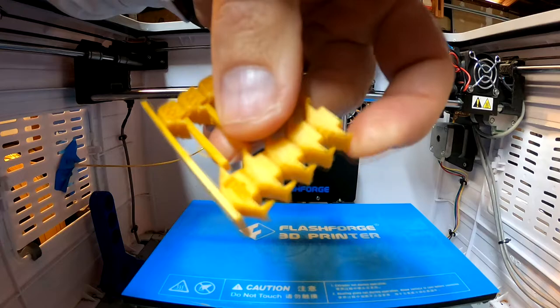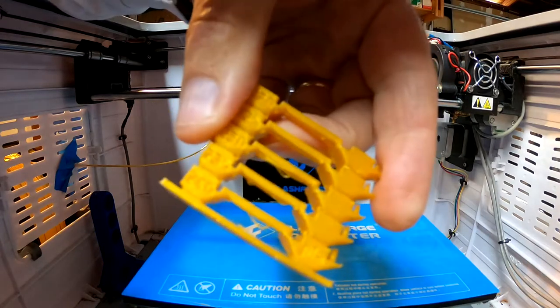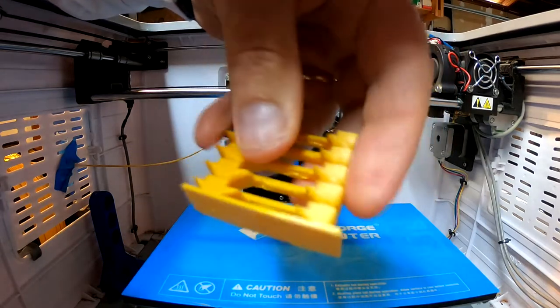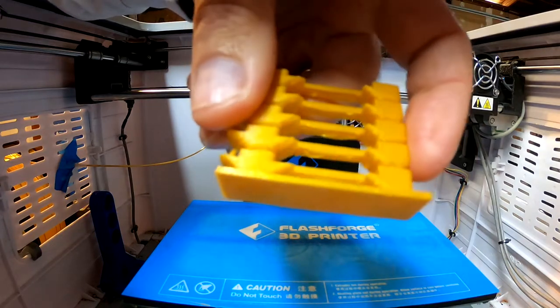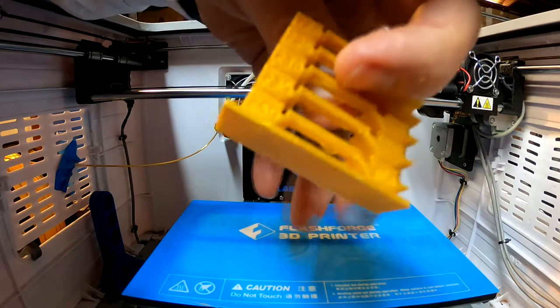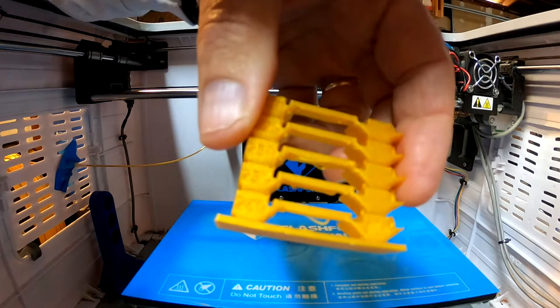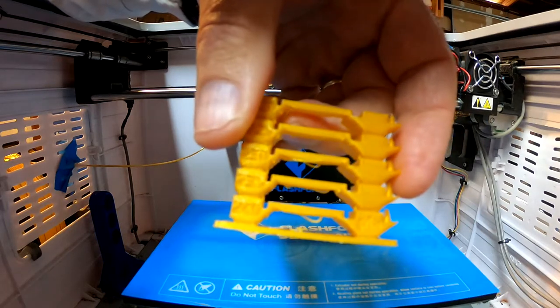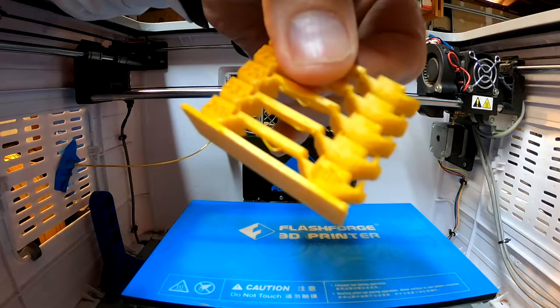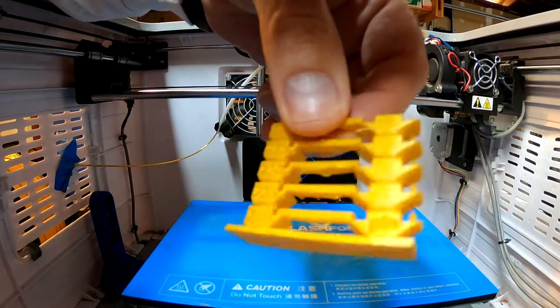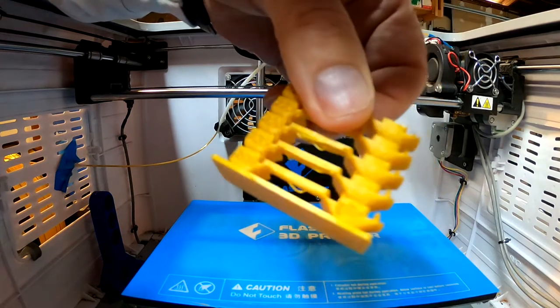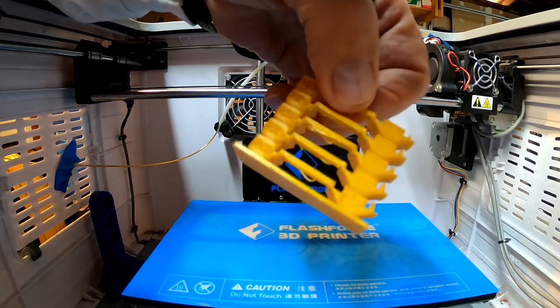Let's take a look at the pointy things. A little bit of blobbing on the 220. 225 looks the best in my measurement here. Let's look at the back. There's drooping on the higher temperatures, 230 to 240. I think 225 it is. The pointy thing is a little bit better on 230, so I guess we'll go with 230. That's what we've been printing other filaments at. Hope it doesn't make that much difference, and we should get better layer adhesion. So let's go ahead and print the bed and layer adhesion test at 230.